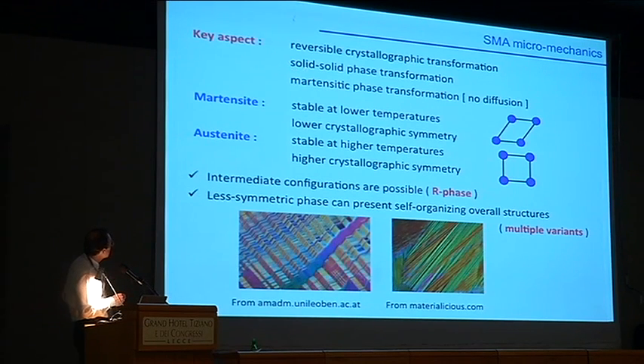And the basic ingredient you have to understand is that the material has such unusual effects because inside the material there is a reversible crystallographic transformation. So the material is able to show this reversible crystallographic transformation. That is a solid-solid phase transformation, which is also sometimes named martensitic phase transformation. So basically you have two phases, martensite and austenite, and the material is able to transform, with certain features, from martensite to austenite and back.